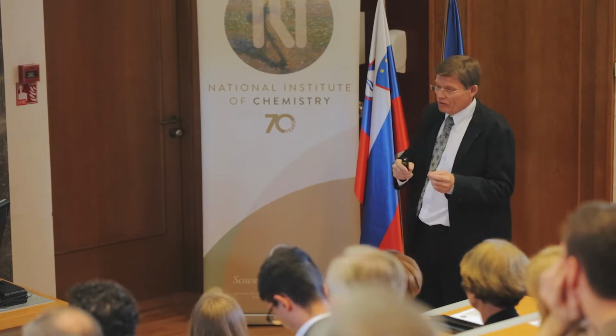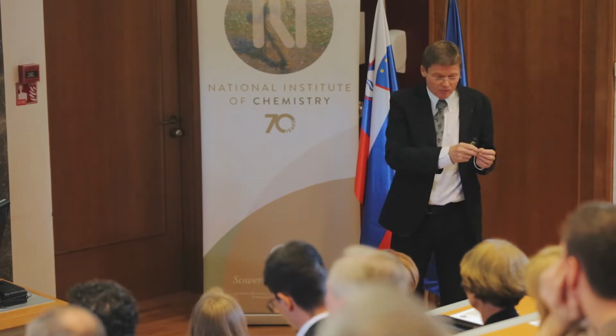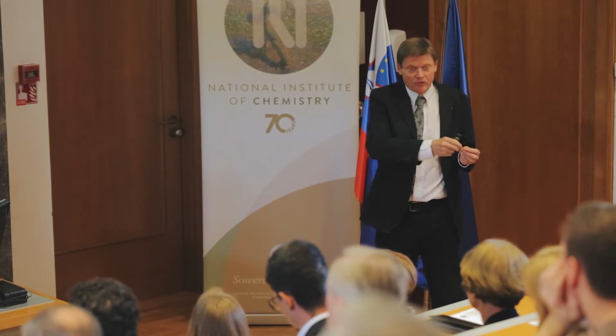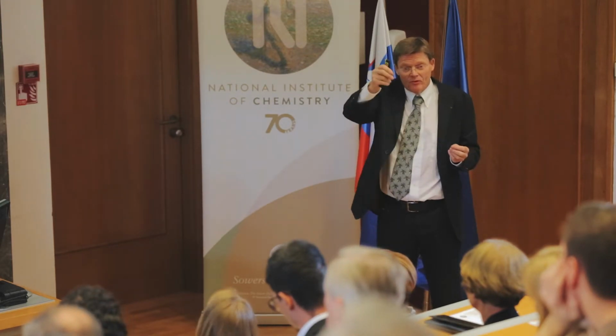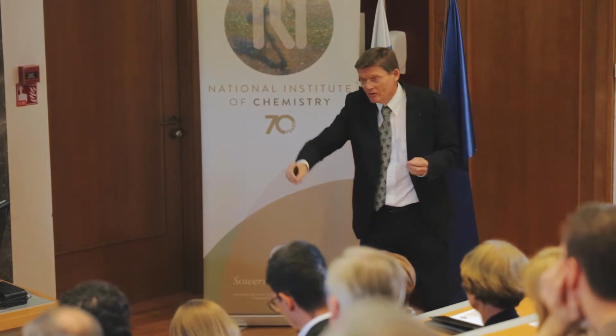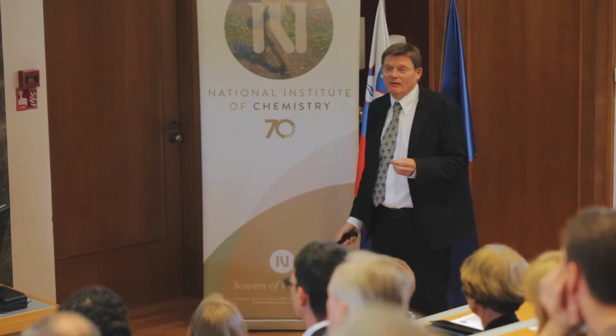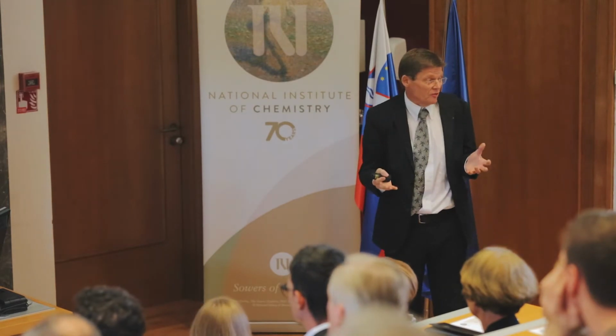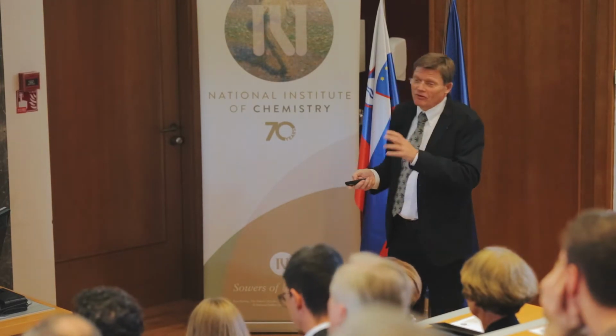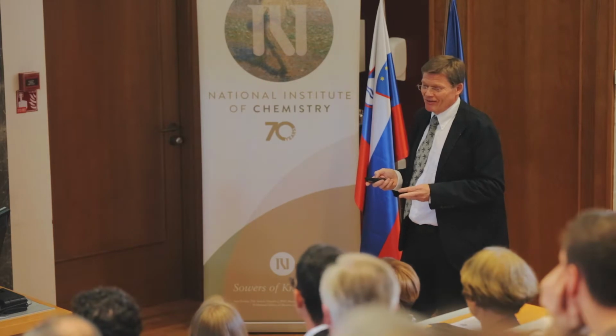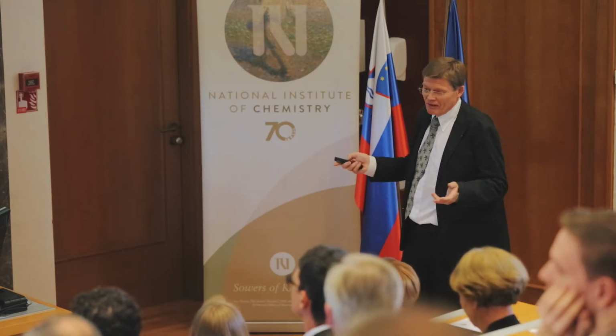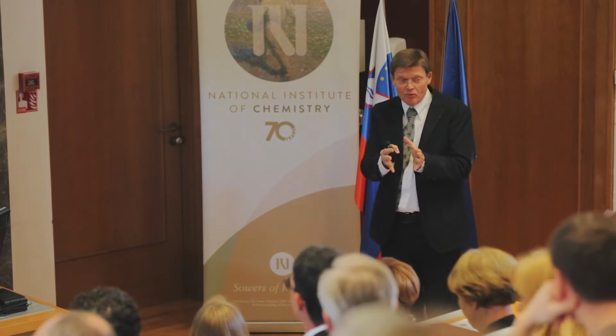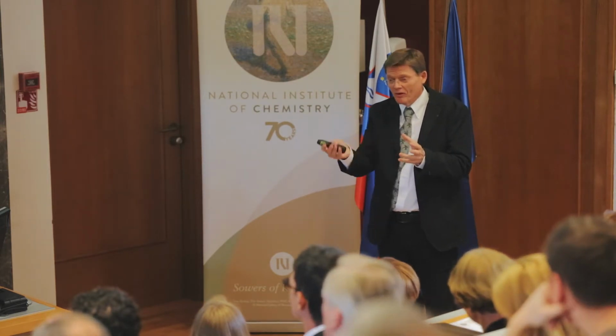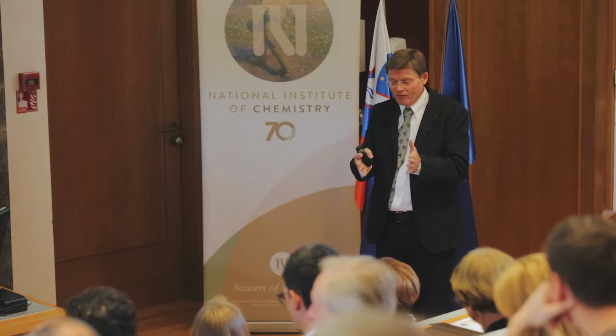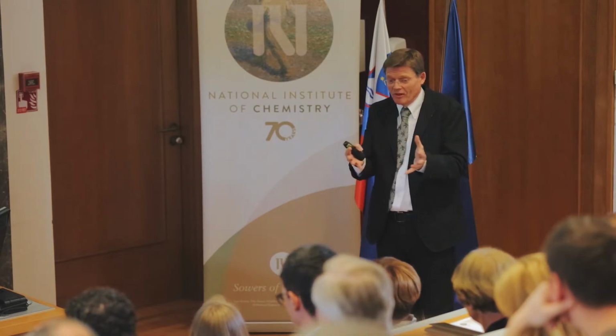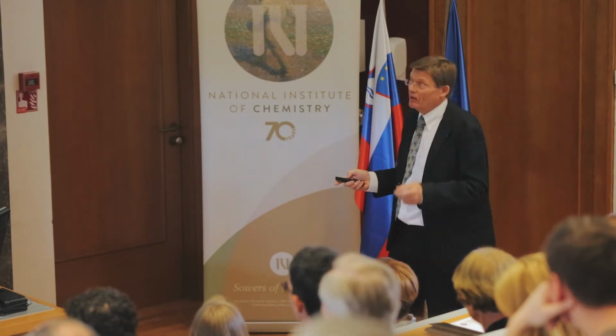Second, when you do this kind of sweep experiment, electrochemists do a kind of current ramp, increasing the current with the voltage, then they decrease it, and then they found hysteresis that they could not explain. So we thought this is all very much characteristic of a mixed conductor with phases which do block the ions. Normally you don't care about ions, so the phases that you have left and right of this perovskite are just electronic conductors. They would block the ions.